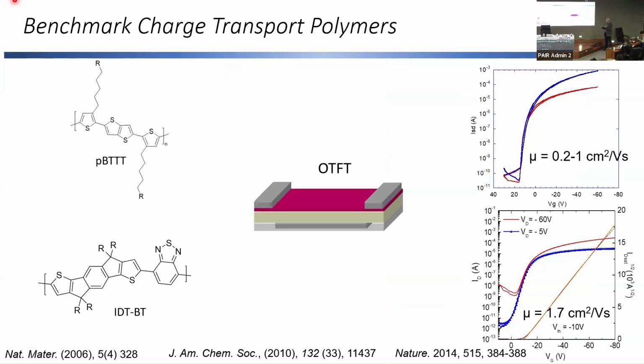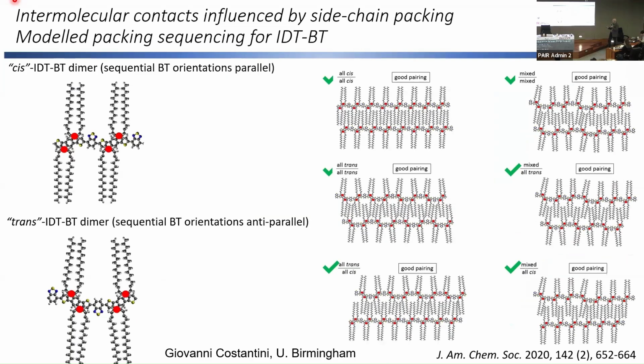Here is our transistor, and you can see here now, in fact, IDTBT, which is a much lower order, less crystalline, we don't see evidence of the crystallinity, has actually got a much higher carrier mobility. So very nice characteristics. So this was a real puzzle, why something with much lower order should give a much higher charge transport. And we went back and we looked again at the side chains and the modeling.